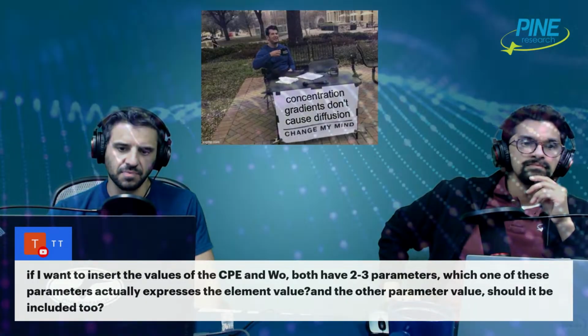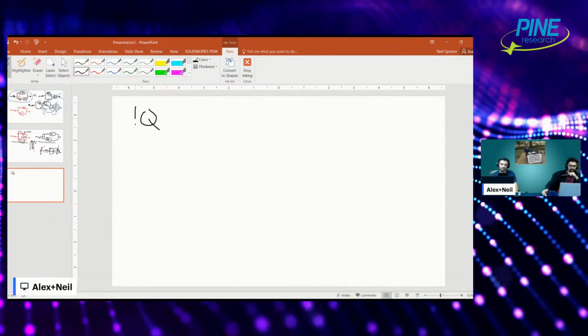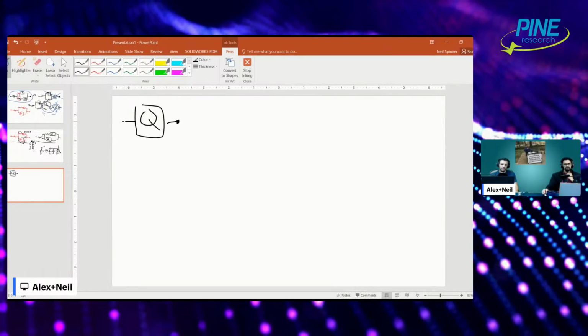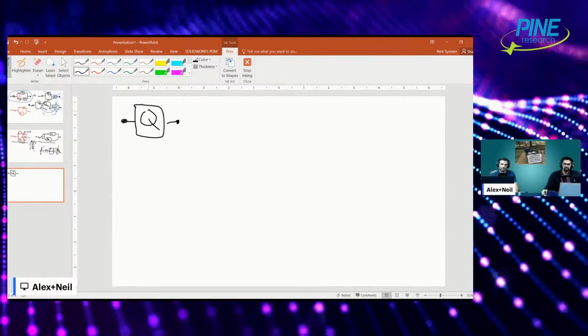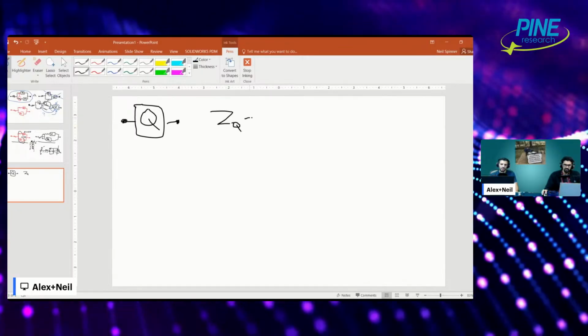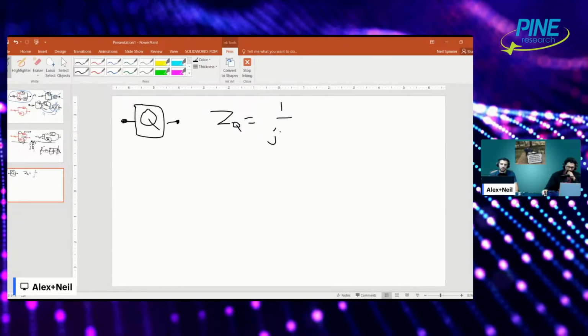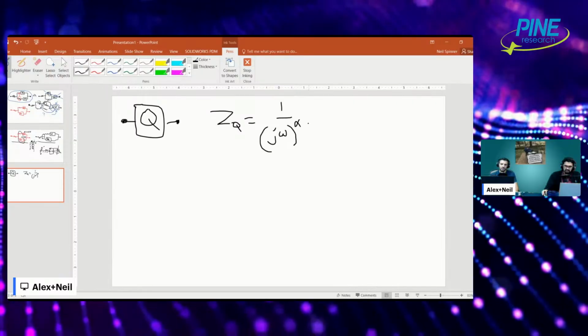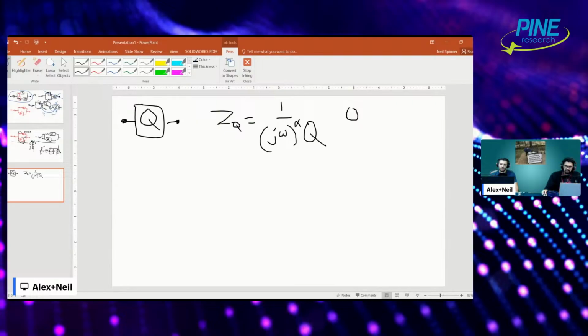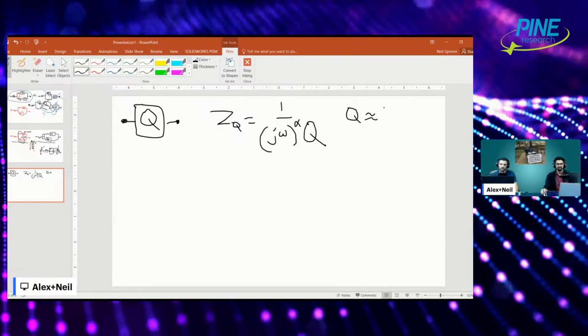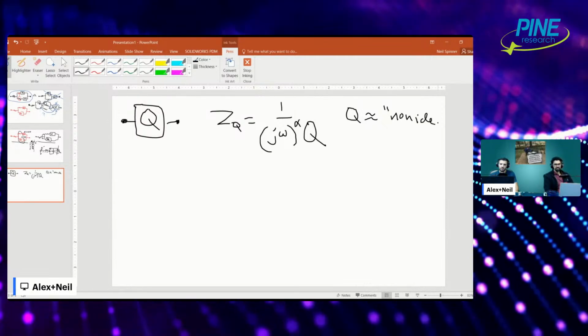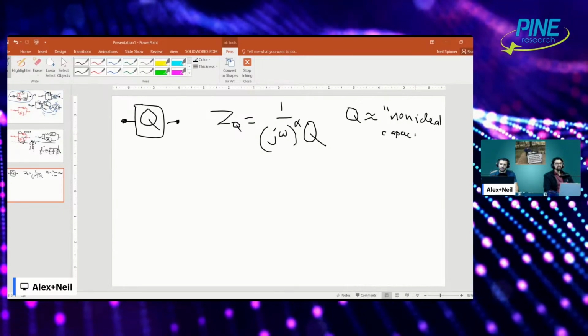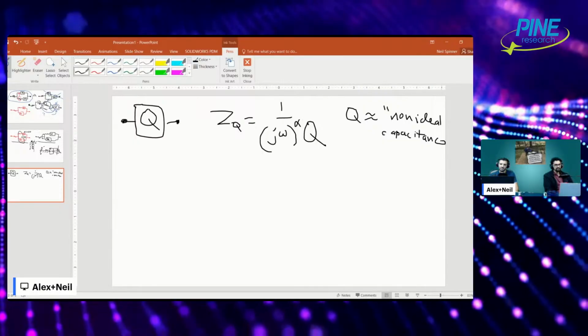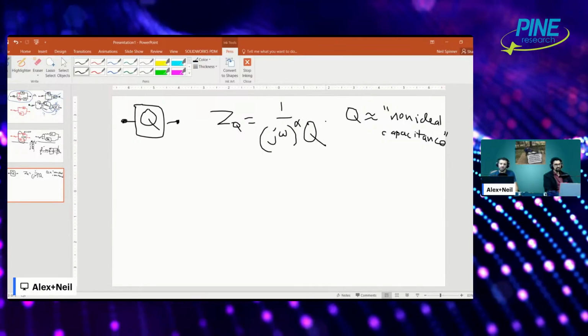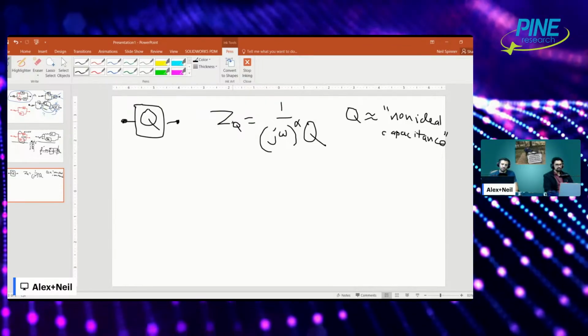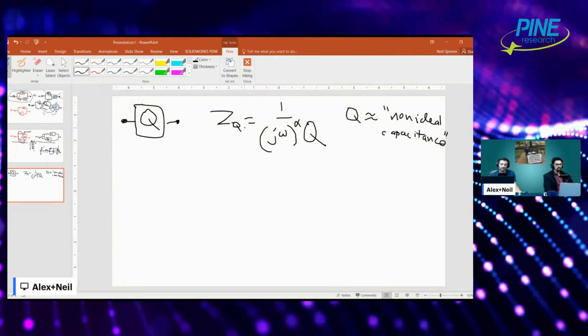So for instance, just as a matter of definition, with a CPE, we typically use Q or CPE. Sometimes you put the letters CPE in here, but typically it's Q. The impedance of my CPE is equal to 1 over j omega to the alpha times Q. Q is what we sort of think about as almost like non-ideal capacitance. Now it's tricky because if alpha is 0.5, it's actually like infinite plane diffusion. It defaults to a Warburg, but typically the CPE is used to model capacitive elements that are behaving in a non-ideal fashion.